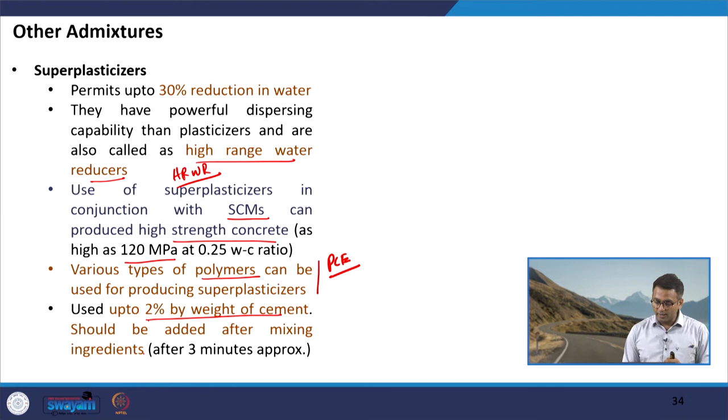It is recommended that superplasticizer be added after mixing the ingredients. You mix the aggregates, sand, cement, and some water, then apply the superplasticizer and remix. Alternatively, a portion of water is kept separately — the concrete mix is made with the remaining water, and then the reserved water along with the superplasticizer is added finally and mixed for a few more minutes. This method makes superplasticizers work better than if added initially.